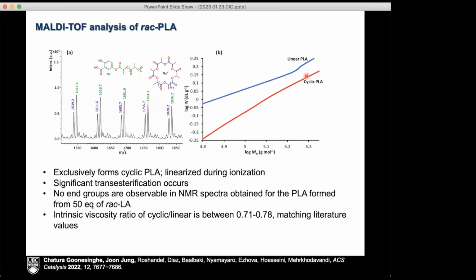We can also, very importantly, look at this plot, which is comparing the viscosity of these materials, the ratio of intrinsic viscosity between the linear polymer and cyclic polymer. You can see that the cyclic polymer is about 75% of the linear one. And this matches literature values for cyclic PLA. So clearly in this system, we were generating cyclic PLA.